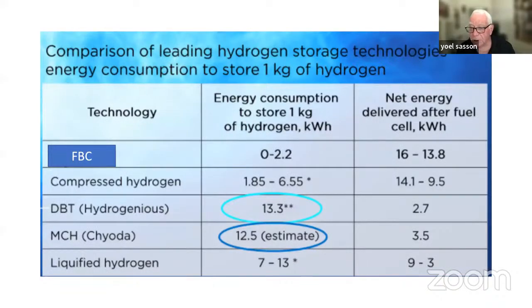So the most important issue now, when I compare different techniques including the Chiyoda technique, is the energy needed for the process. In Chiyoda, you need a lot of energy for the process. Normally, energy consumption to store 1 kilogram of hydrogen is measured in kilowatt hour. In the case of Chiyoda, it's 12.5 kilowatt hour, while the energy you have altogether in hydrogen is about 16 kilowatt hour per kilogram.